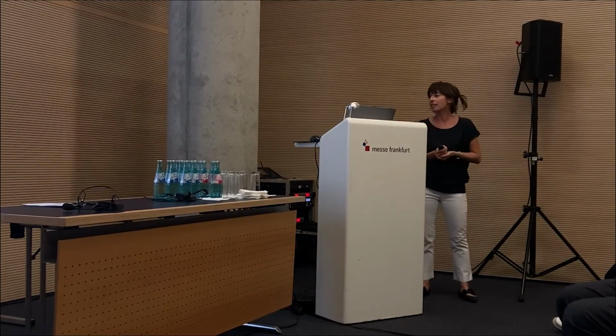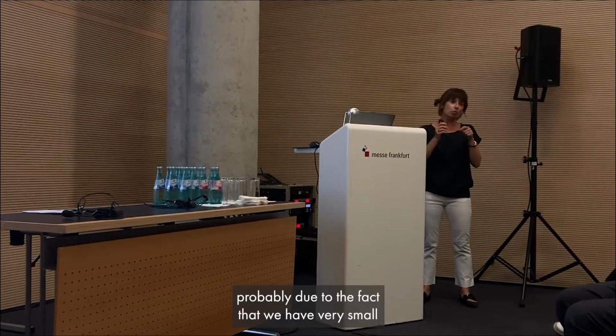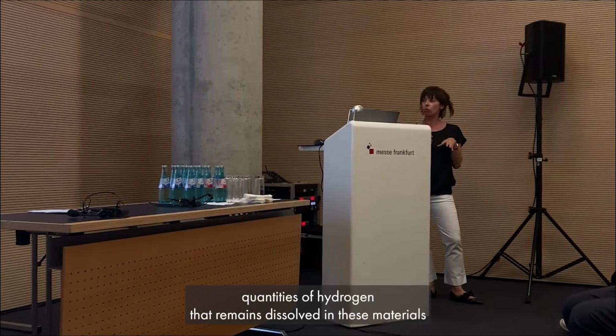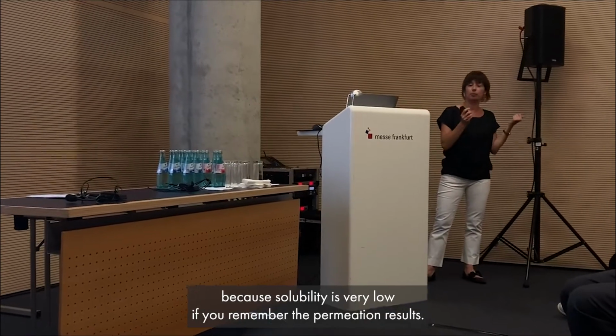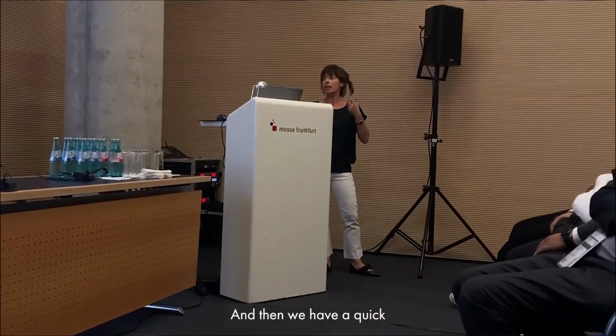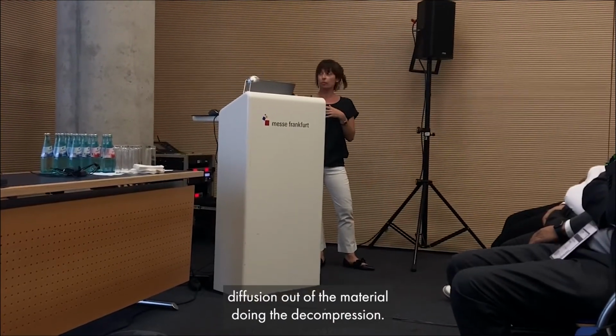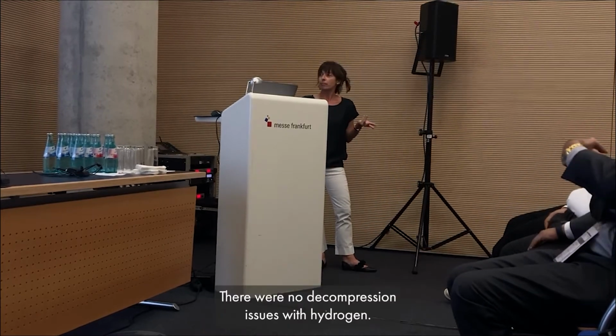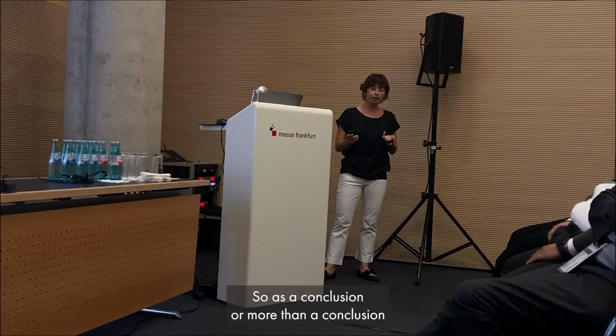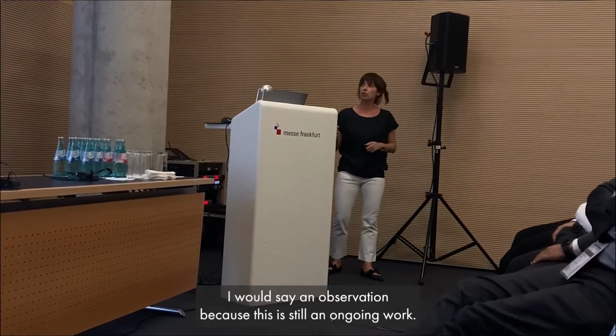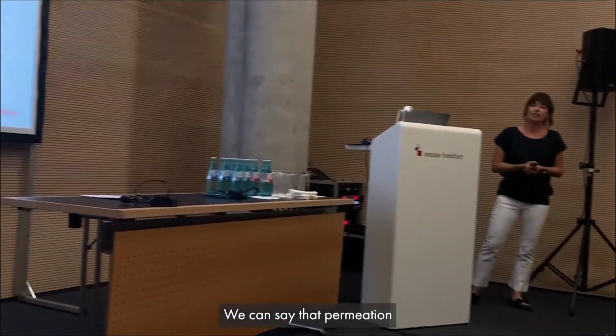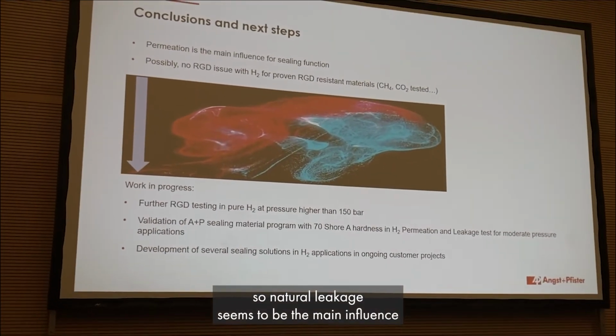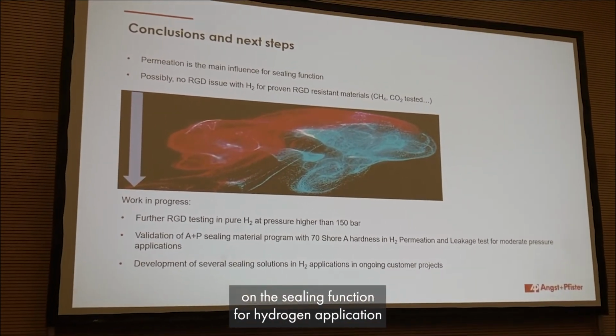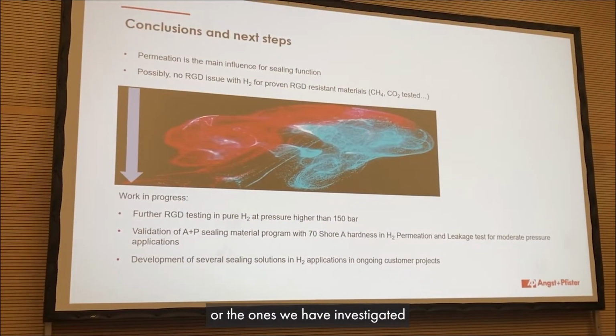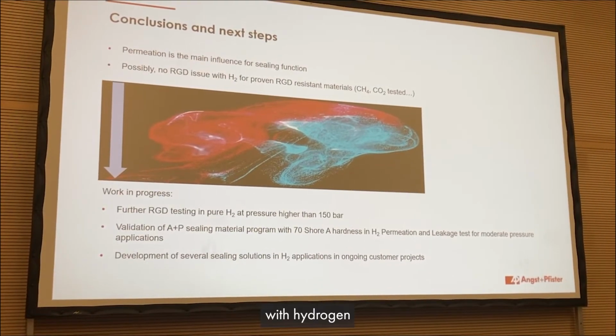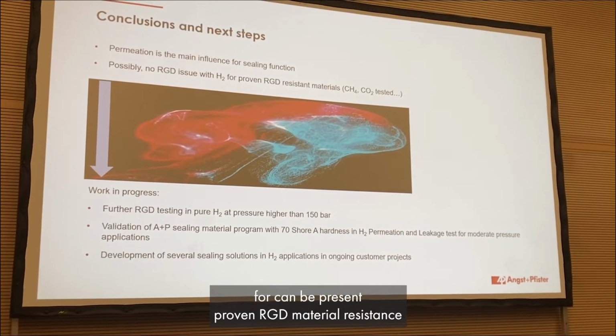So, as said, it's probably due to the fact that we have very small quantities of hydrogen that remain dissolved in this material because solubility is very low, as you may remember from the permeation results. And then we have a quick diffusion out of the material during the decompression. It looks like there were no decompression issues with hydrogen. So as a conclusion, or more than a conclusion, I would say an observation, because this is still ongoing work, we can say that permeation, so natural leakage, seems to be the main influence on the sealing function for hydrogen applications, or the ones that we have investigated. Possibly no RGD issues with hydrogen can be present for proven RGD resistant materials.